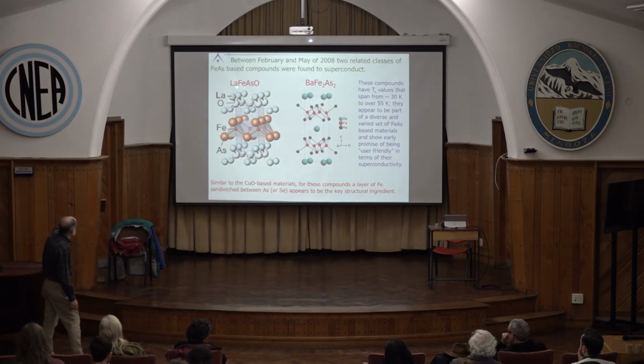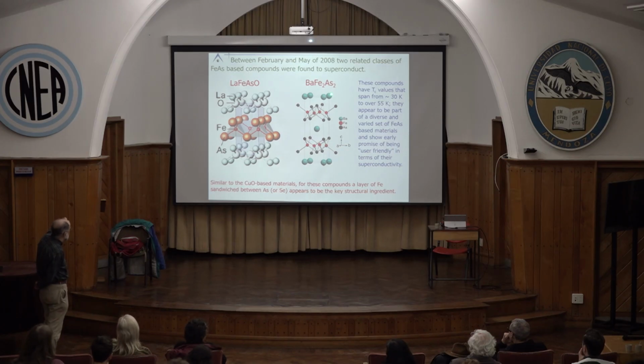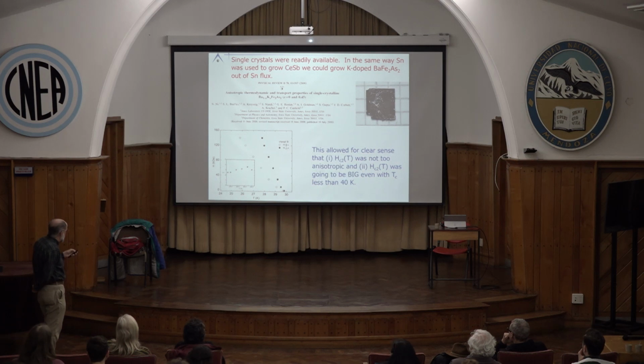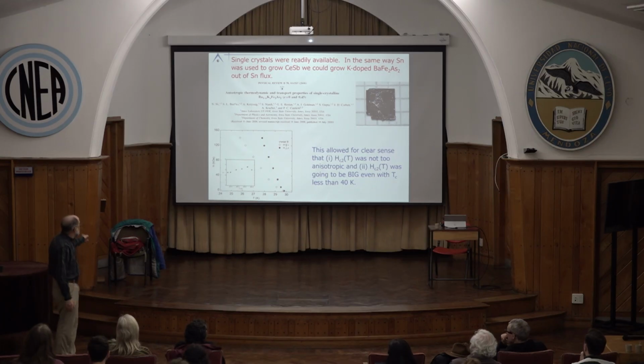So the first two families were lanthanum iron arsenic oxygen, which was interesting, but a bit of a pain in the backside to make, and barium iron 2 arsenic 2, okay? And the neat thing is, barium iron 2 arsenic 2 falls exactly into how we grew cerium antimonide. Remember, we grew cerium antimonide out of tin? We could grow barium iron 2 arsenic 2, doped with some potassium, out of tin.